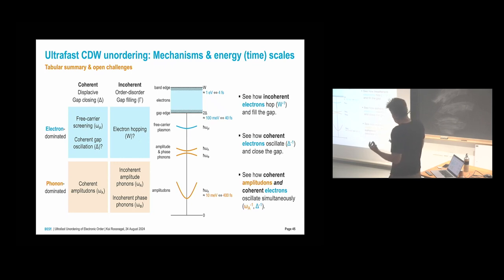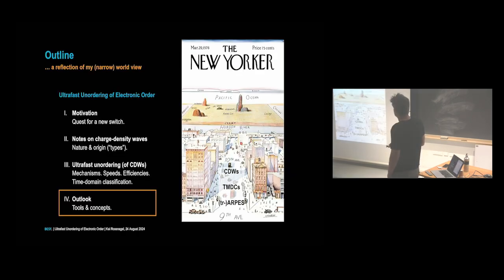And also, we have always looked at these coherent phonon vibrations. This you can easily see in electronic structure. But I would like, for example, in a spin density wave, or possibly in this titanium diselenide, where you have this electronic component, I want to see a coherent electron oscillation on the fundamental time scale given by the gap size. And if I see those, then I also want to see it together with a coherent oscillation of the phonons, and then maybe see some interaction effects.